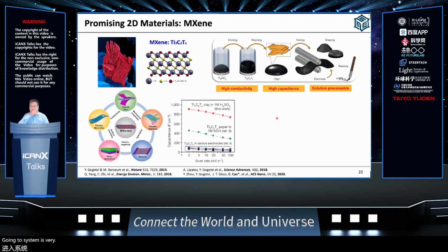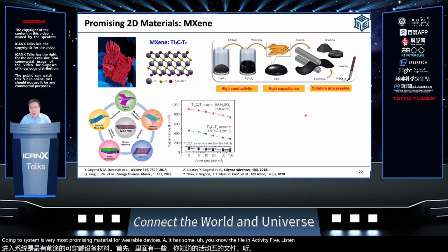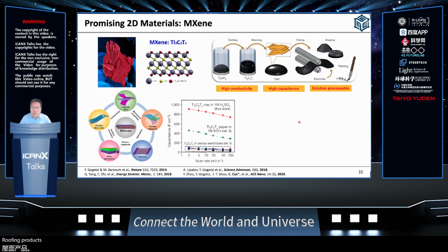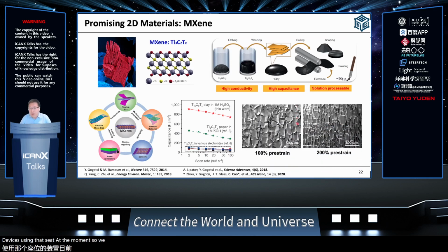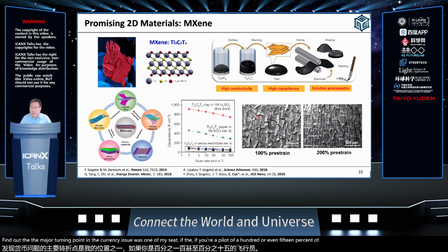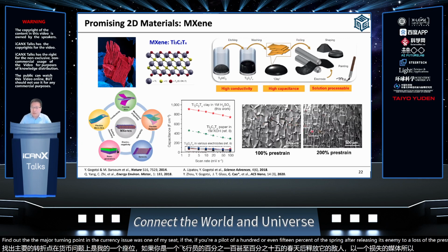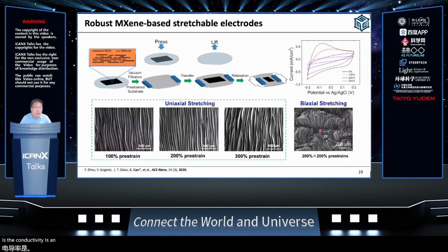MXene is one of the most promising materials for wearable devices. It has high conductivity and high capacitance. It's also solution processable. However, we found that there was little work on stretchable devices using MXene at that moment. So we found the major challenge is the cracking issue of MXene. If 100% or even 200% strain is applied, after releasing it generates a lot of cracks. So this affects its conductivity significantly.